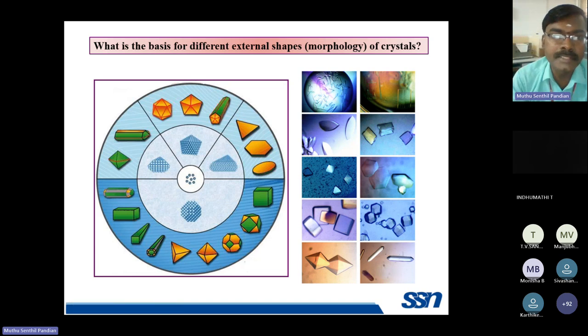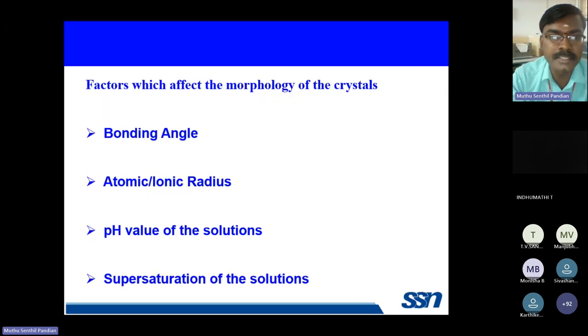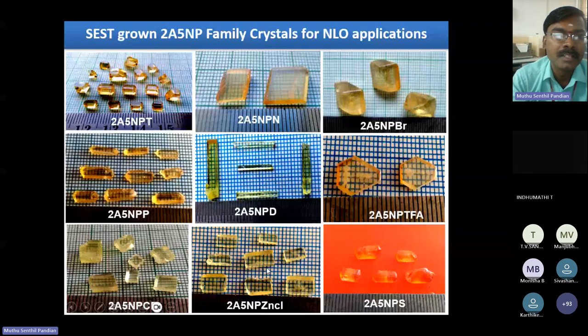So what are the bases for the different external shapes of the crystals grown by this SEST method? These are some of the factors which affect the morphology of the solution grown crystal: bonding angle, atomic and ionic radius, pH value of the saturated solution, and the solution we prepare for the conventional method, and the supersaturation of the solution. These are some of the conventional method grown 2A5NP, 2-amino 5-nitropyridine derivative single crystals for nonlinear